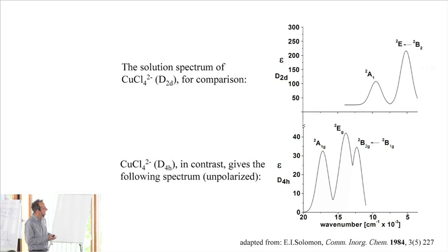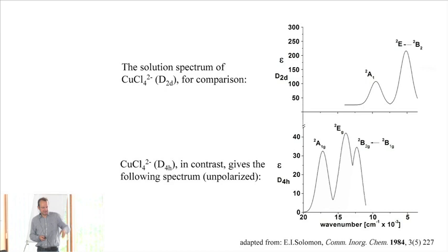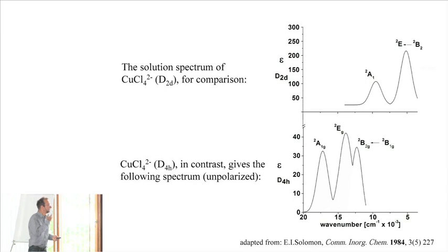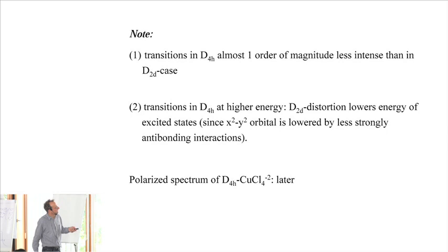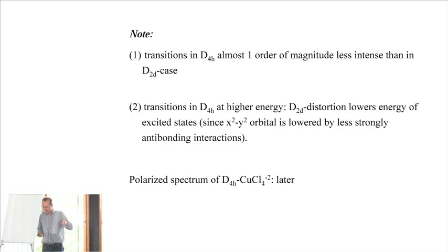And this is, of course, due to the fact that the static distortion gives you more effective elimination of the center of inversion than just the vibration. The transitions in D4h are almost one order of magnitude less intense than in the D2d case, and they are at higher energy, because the D2d distortion lowers the energy of the excited states, since the x square minus y square orbital is lowered by less strong antibonding interaction. Okay,